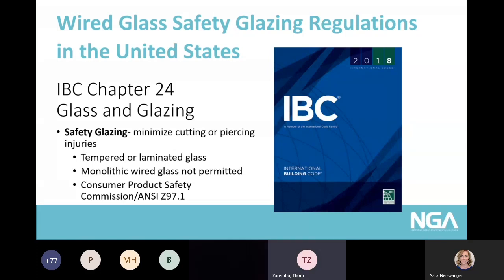But back before 2012, all 3 categories, 12-inch drop, 18 and 48-inch, were all categorized in the United States as safety glazing. And up until even more recently, as we'll get to in a moment, in Canada, the only safety glazing standard that existed in Canada was for wired glass, and it was at a 12-inch drop height or 100 foot-pounds. So is it now a safety glazing? No. Wired glass has been eliminated from the safety glazing category, both in the United States building codes and in ANSI Z97.1. The 12-inch drop height has been eliminated from ANSI, and monolithic wired glass, that means just annealed wired glass with no organic or other coatings on it, is no longer considered a safety glazing in the United States.